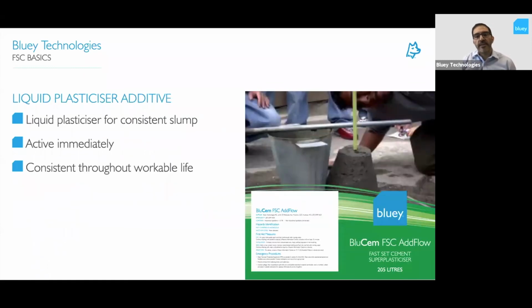We've also added some changes to the raw ingredients. One thing we realized was that the product itself on mixing was changing in its rheology over time. So as it came out, it had a fairly low slump. And then after about 2 or 3 minutes of vibration, it had a really high slump. And what we're finding is that the plasticizers that were being added in a powder format were taking a few minutes to dissolve. So we actually converted those to a liquid plasticizer, which means that they were active immediately.